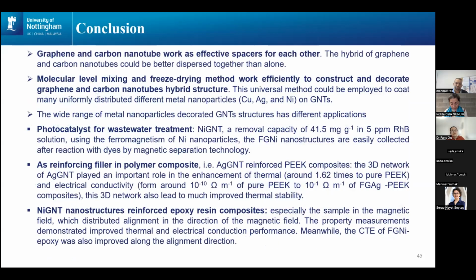So here comes the conclusion. We have confirmed that graphene and carbon nanotube work effectively as a spacer for each other, so we can combine them together and get better dispersion. Using molecular level mixing and freeze drying methods, we effectively construct and decorate graphene and carbon nanotube hybrid structures, and a wide range of metal nanoparticles can be coated onto our structure.